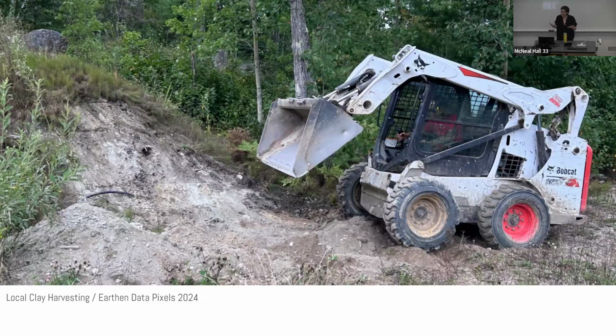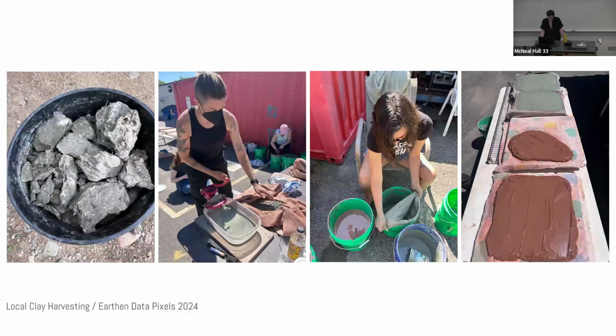And then something else that we did that first year is that we were really interested in less extractive, hyper-local material sourcing. So a friend in Ely, Minnesota, with a property rich in clay and a bobcat allowed us to harvest some on his site. We brought it back to the Twin Cities. We ground it, we sifted it, we added sand from White Sand Beach as temper, a very labor-intensive process that only lasted a summer. But we're thinking about picking up that thread again in the coming years.